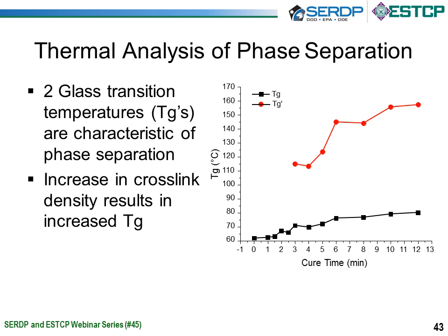However, as we start to cure the polymer coating, we see a second glass transition appear at approximately 3 minutes. This appearance of the second glass transition temperature confirms the domain formation as we originally believed. And this continues to increase the glass transition past 8 minutes, which also confirms that we have continued cross-linking systems even after the domain has formed, which is essential for the durability of the coating system.